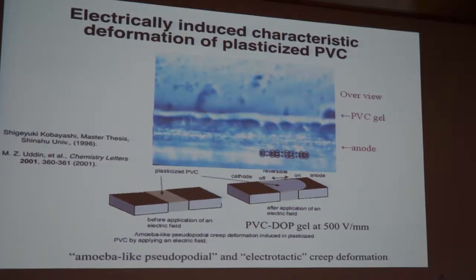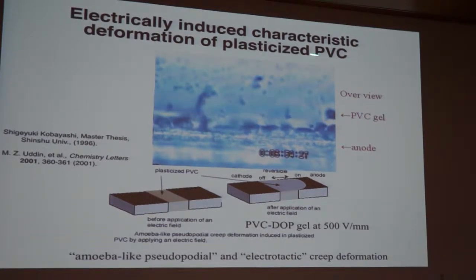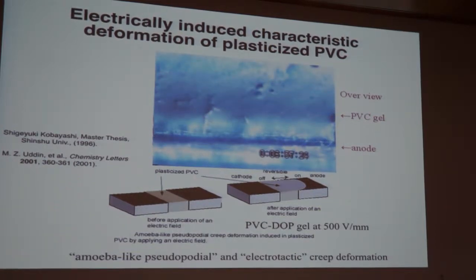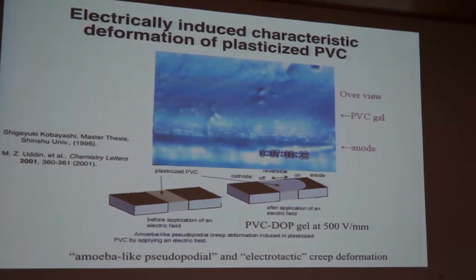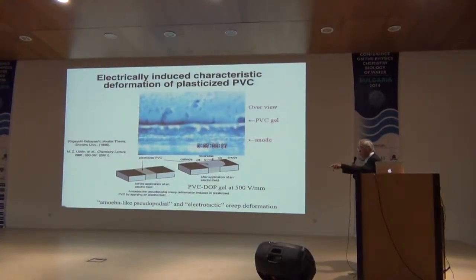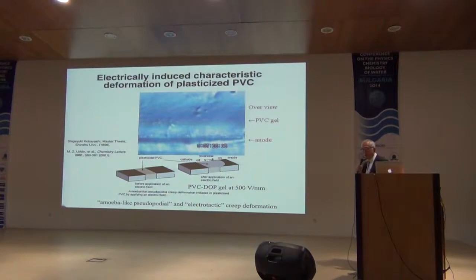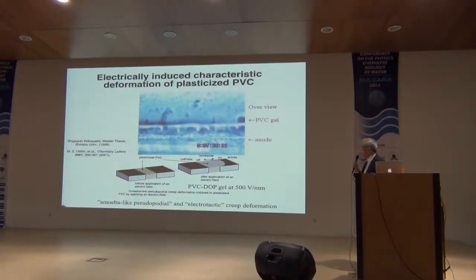First, what kind of strain can be seen for the PVC gel? This is the anode surface. This is a transparent gel. And when we turn on the field, the gel creeps out onto the anode surface. This is a strain induced on the very edge of the anode, only the anode surface. The cathode surface didn't show any change. So this is very peculiar. And this is the illustration of the deformation. We call this amoeba-like pseudopod and electrotactic deformation. So far, PVC is the most successful material for this kind of deformation.